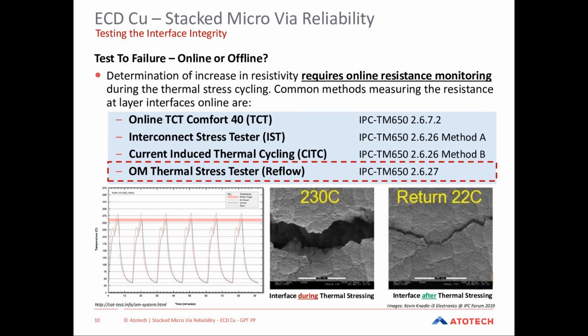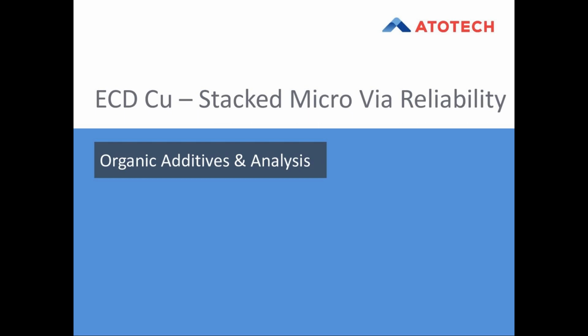So famous online testing methods are thermal cycle methods, interconnect stress testing, but you also see here again in a red box highlighted the OM thermal stress tester. It is, during a reflow simulation, determining the resistance increase of interfaces between stacked microvias. And here you get a very clear feedback and a very clear result in regard to reliability. This method is very important, as I said, nowadays, to judge if your process optimization really ended up improving the quality of the build-up. So now let's continue with the electroplating process itself.